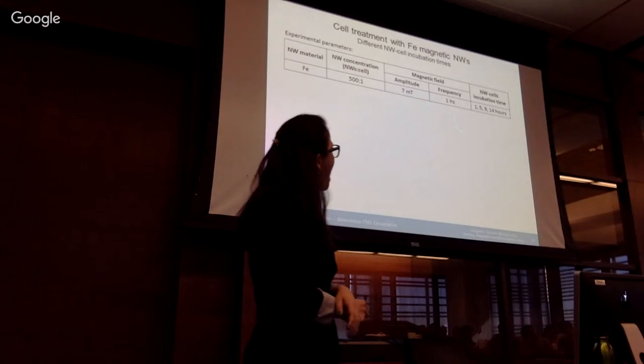Second round of experiments. The material now was only iron at the 500:1 concentration. I increased the field amplitude. I want to see what happened when you have higher forces associated. And I stuck to 1 hertz frequency, as the frequency didn't have an effect. And I incubated for 4 different time points here. And these are the results.